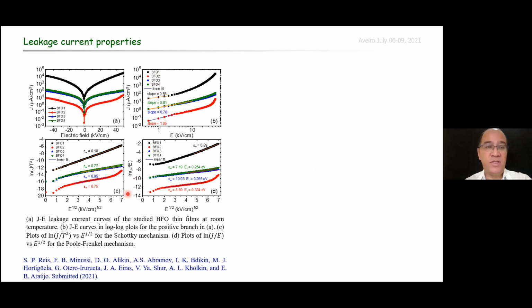We verified the possible Schottky mechanism in this figure C. Despite the excellent linear fit as shown in these figures, the obtained dielectric permittivities at optical frequencies were unrealistic, as observed in this figure. So the Schottky mechanisms were discarded for all our studied BFO films. On the other hand, we checked for the possible Poole-Frenkel mechanism in this figure D. In this case, the linear fits in this figure D lead to consistent values for the optical dielectric permittivity.